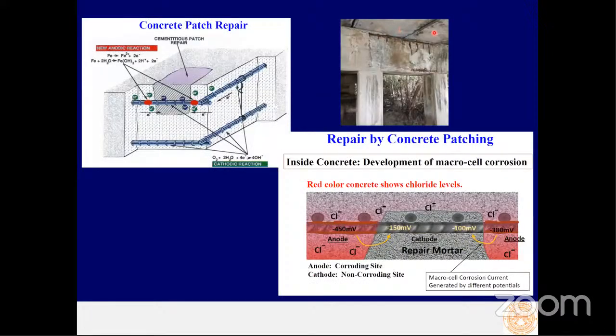Basically, when we find damage like that to the substructures, we check that the concrete is delaminated and the existing reinforcement has formed corrosion, and the area of the reinforcement is reduced. If it's reduced by not more than 30% in the cross-section area, we do some very simple methods. We remove the delaminated concrete, apply epoxy coating to the existing reinforcement, and do concrete patching. In the past, we used it a lot because it's simple and very cheap.